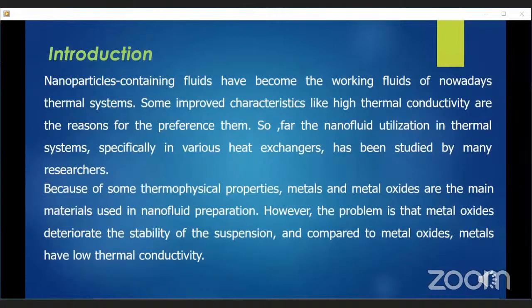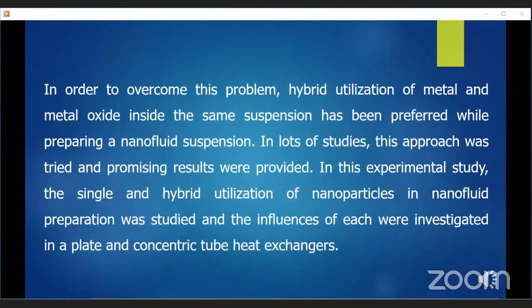However, the problem is that metal oxides deteriorate the stability of the suspension, and compared to metal oxides, metals have low thermal conductivity. To overcome this problem, hybrid utilization of metal and metal oxide inside the same suspension has been preferred while preparing a nanofluid suspension. In a plenty of studies, this approach was tried and promising results were provided. In this experimental study, the single and hybrid utilization of nanoparticles in the nanofluid preparation process was studied, and the influences of each were investigated in plate and concentric tube heat exchangers.